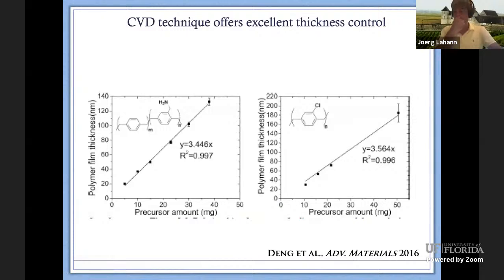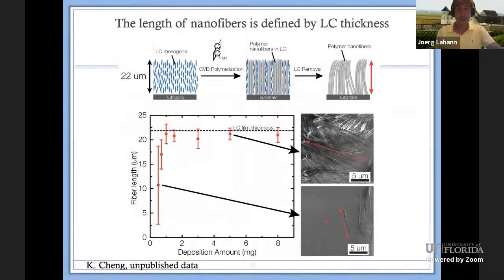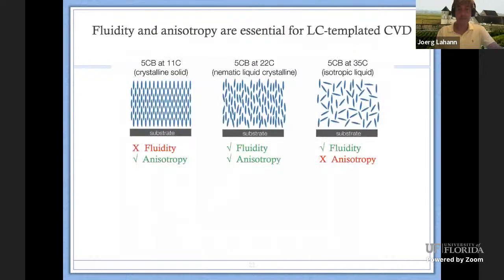Now the thickness of this polymer is very well controlled. So we show you two examples here. And that's another salient aspect of this work, that through CVD we can control the thickness very nicely. That's important here as well, because as we control the thickness, we can then understand the growth kinetics of the nanofibers in those LC phases.